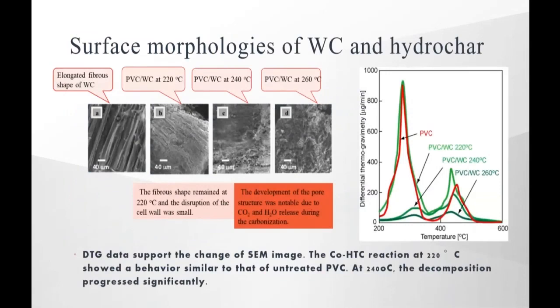This slide showed you the surface morphologies of the initial wood chip and hydrochar. You can see the elongated fibrous shape in the initial wood chip. When pyrolyzed at 220 degrees C, the fibrous shape still remained and the disruption of the cell wall was small. Pyrolysis at 240 and 260 degrees C, the surface morphologies were greatly changed.